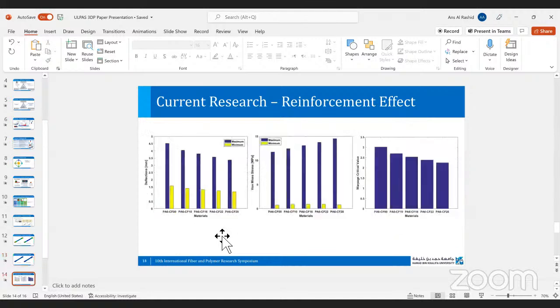So if we look at this graphical form, you can easily see the deflections for the pure polyamide 6, where no carbon fiber was used, we have a maximum deflection from the design values. But by increasing the carbon fiber reinforcement, you can significantly reduce these deflections. And ultimately, if you look at the right, the warpages can also be significantly reduced. But it causes the von Mises stresses, which we also call the residual stresses, to increase a little bit as compared to the pure polyamide.